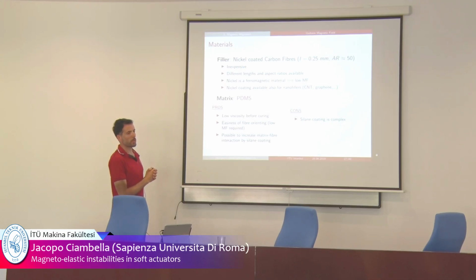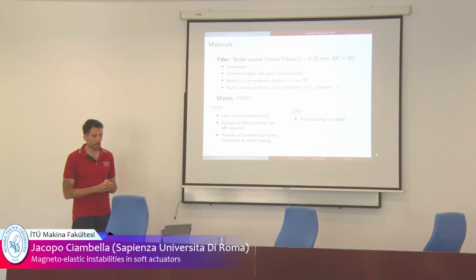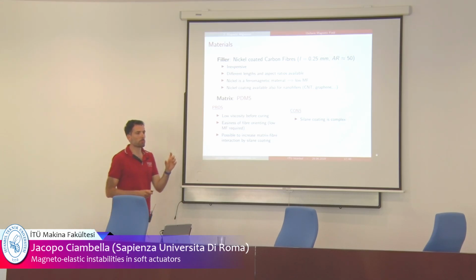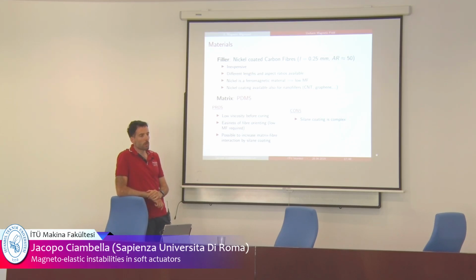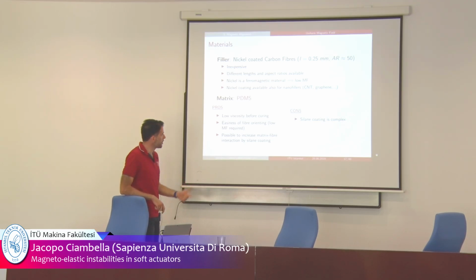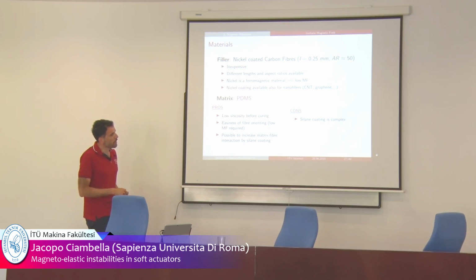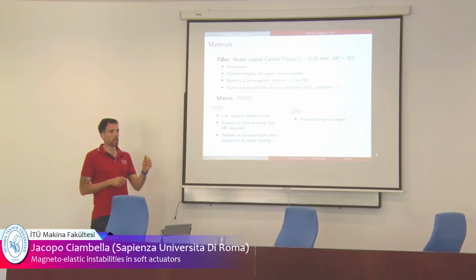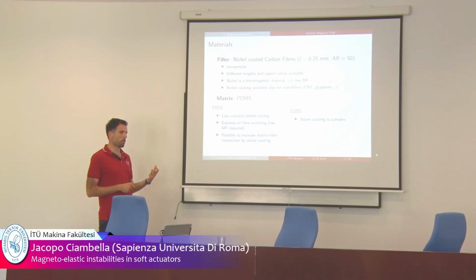This is what we use. Let's see some experimental results now, our results. The fillers are nickel-coated carbon fibers. The length is 0.25 millimeter, so an aspect ratio around 50. Why do we use nickel-coated carbon fiber? Because they are inexpensive, they're easy to manufacture, they can be bought from the market, and because of the nickel coating, the field you need to apply is relatively low. As I said, we won't go up to 0.1 Tesla, but no more.